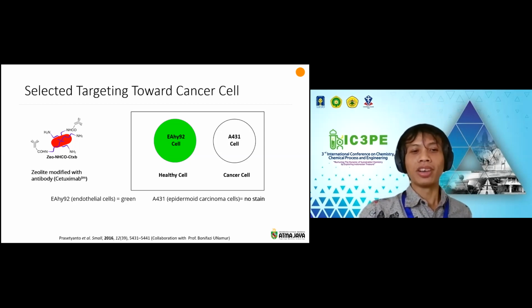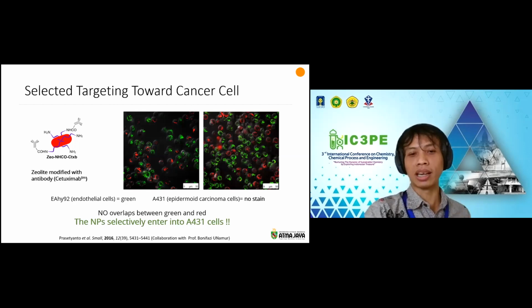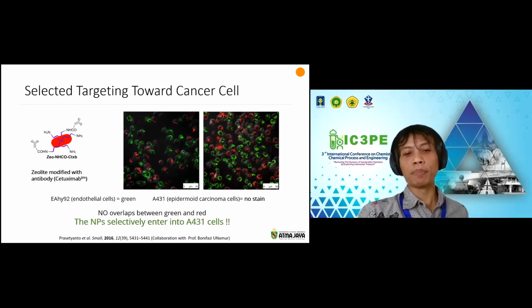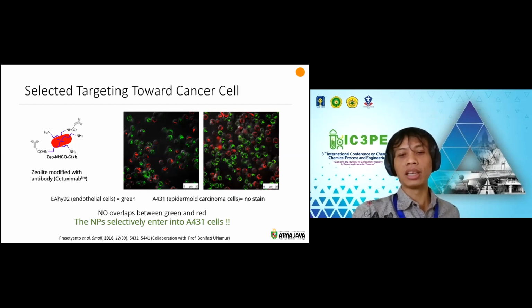So if the zeolite selectively only enters the cancer cell, there will be no overlap between green and red. But if the zeolite also enters the healthy cell, that means there will be an overlap between the red and green. So what happened here? There is no overlap between green and red. It means that our nanoparticle, after modification, can enter selectively into A431 cells. So this is really good news for us that we can target a certain cell.